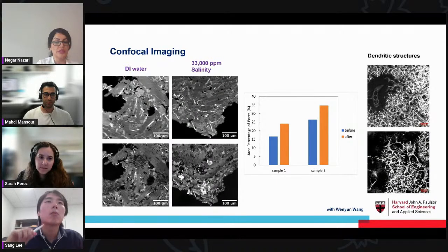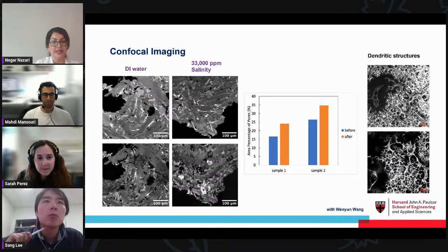But when we checked the surfaces on the exact same locations, the one on the left shows the samples in the DI water before and after the reaction, and the one on the right shows the before and after in the high salinity brine solution. So we observed that, interestingly, in both of the samples, the area percentage of the pores. We only talk about the surface.